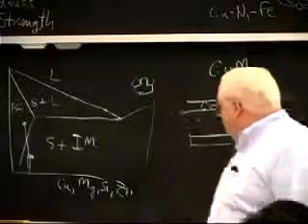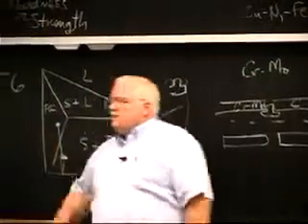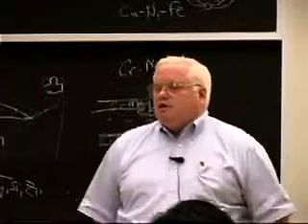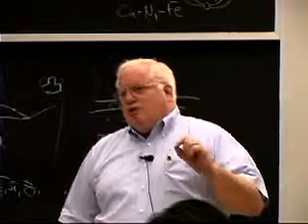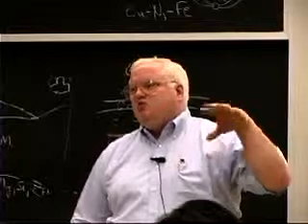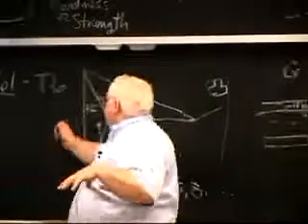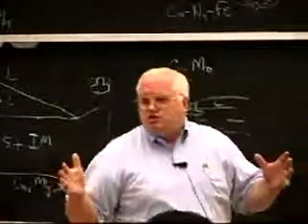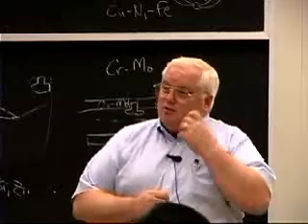In any case, getting back to the aluminum metallurgy, in the 1920s, people learned that you could heat treat these aluminum alloys and get high strength. They actually learned it a little bit earlier than that. These aluminum alloys will actually continue to age even at room temperature. One of the heat treatments, I think it might be the T3 heat treatment, is not artificially aged in a furnace at higher temperatures. It just naturally ages at room temperature. The precipitates will form at room temperature. And so